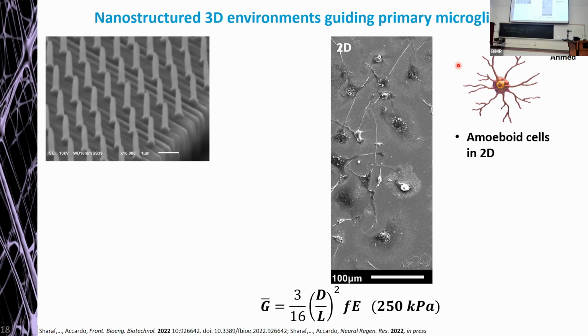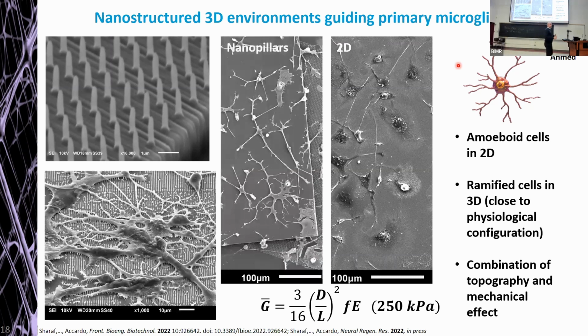Longer, well, taller, thinner, lower effective shear modulus, which can go down in this case to a few hundreds kilopascal, very close to the rigidity of the brain. And that was the result. The microglia like that, and they developed a very well defined ramified phenotype over 15 days of culture.